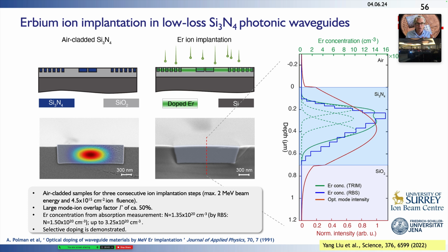Now, the other way to reduce damage is by going to lower energies. In some of the laser devices that we have recently been studying, we have reduced the thickness of silicon nitride from 800 nanometer to just 200, which brings down the energy by about a factor of 4. And there, the implant damage is very negligible. But this was indeed one of the surprises that we found, that the implant damage on the waveguide itself in terms of optical loss is very minor, even at very high energies.